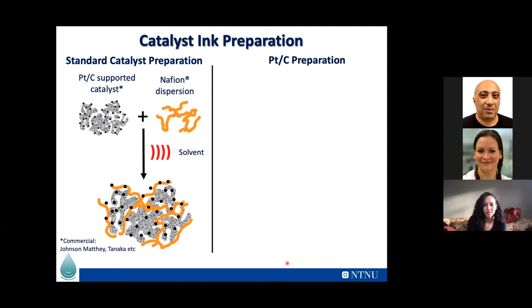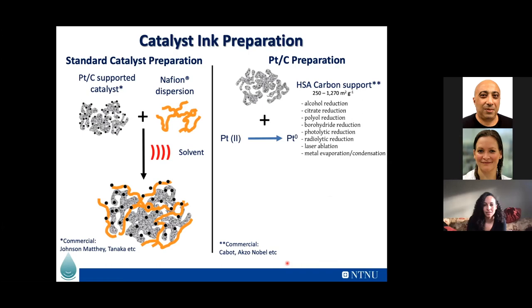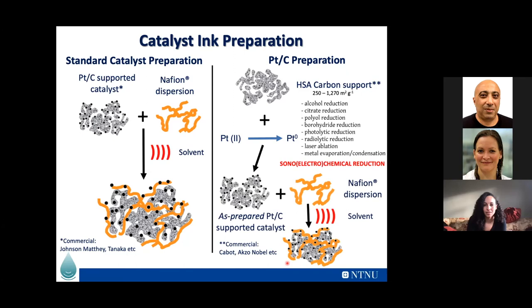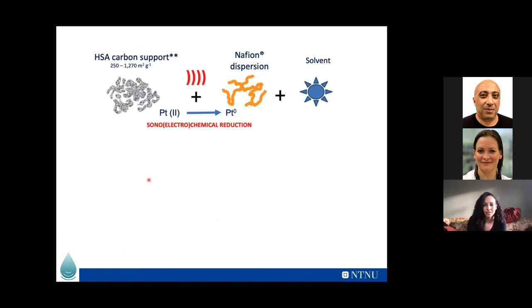Okay, what we are suggesting is that you start with your high surface area carbon support, then you do your electrochemistry, or your chemistry, or your sonoelectrochemistry, sonochemistry on it, and then you do basically the rest of your preparation. So this is what we had in mind, but here we actually extended that work to, okay, let's do that in one pot.